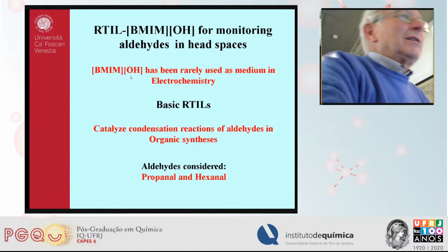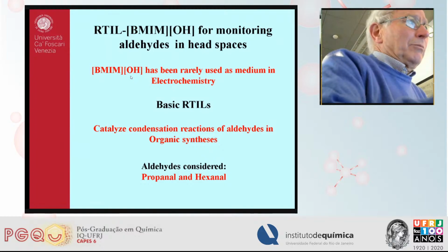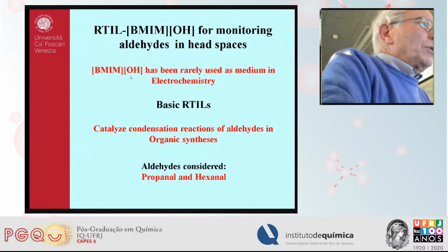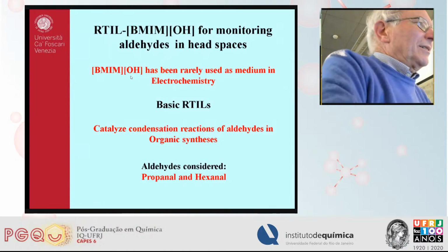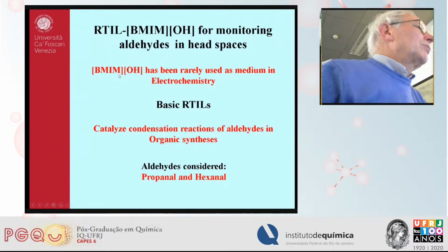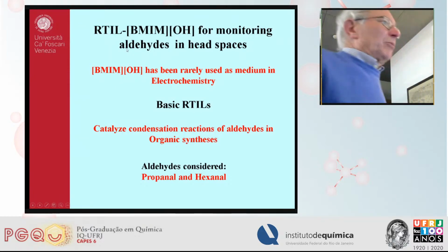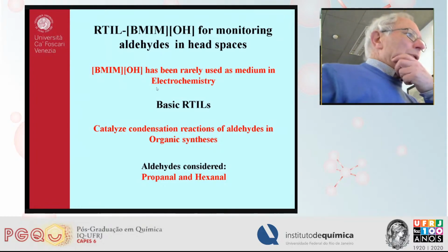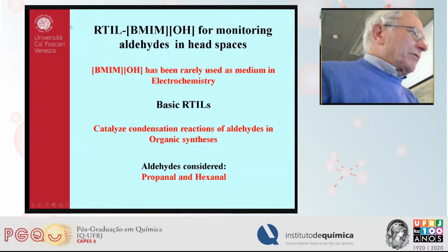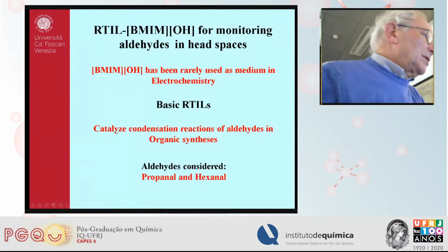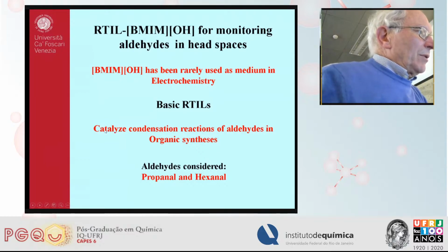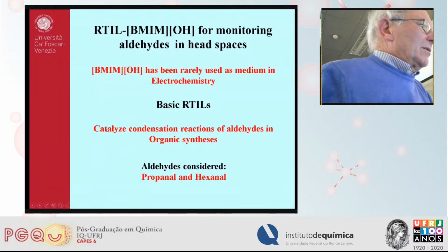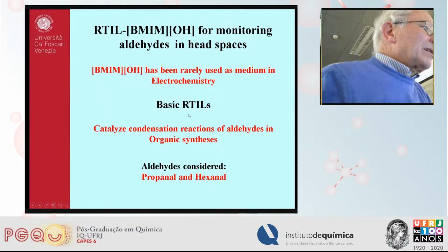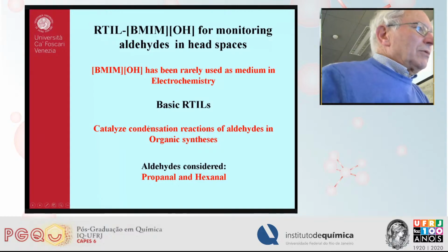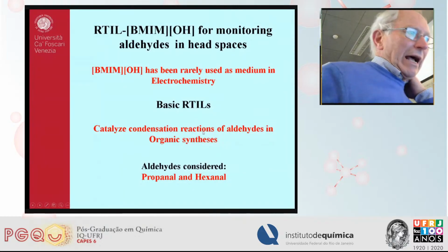Aldehydes in headspace are typically monitored by gas chromatography. So we want to see whether, using this probe and this specific ionic liquid, we could provide a reliable measurement of aldehyde. Why do we use a basic room temperature ionic liquid? Because from the literature, we realized that basic ionic liquids are employed for condensation reactions involving aldehyde, which means they somehow catalyze the aldehyde reactions.